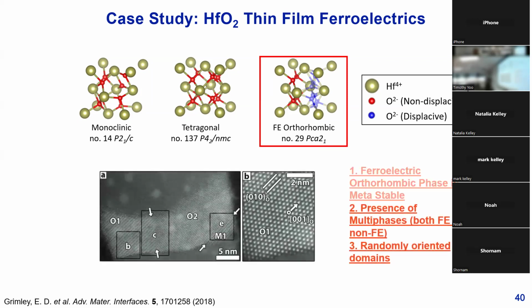We can see in some prior TEM work that some of these grains can be very small and also randomly oriented. We also see in prior work that there have been reports of multiple different types of phases grown all together. Again, this could be both the ferroelectric and non-ferroelectric phases. And because these grains are going to be randomly oriented, again, there's no guarantee that you're going to have these nicely oriented grains to image. And so it's going to be largely a chance. So this is a great application for descent as well as supervised machine learning.